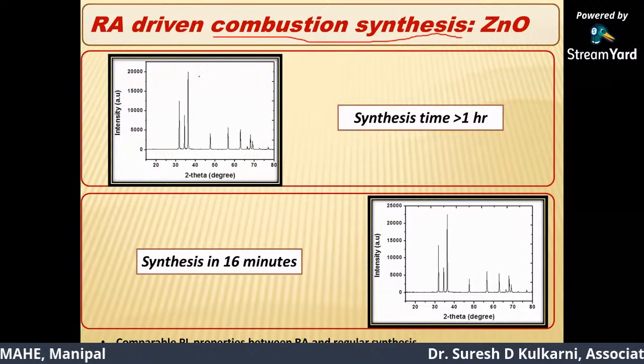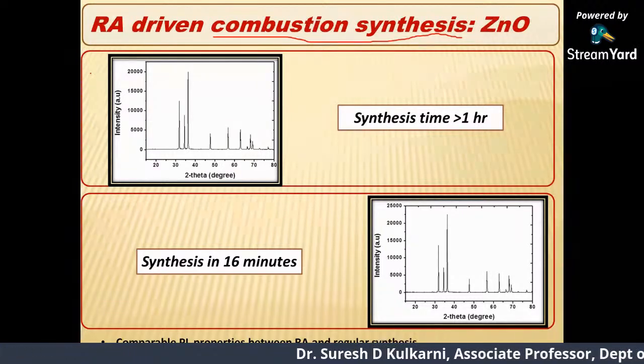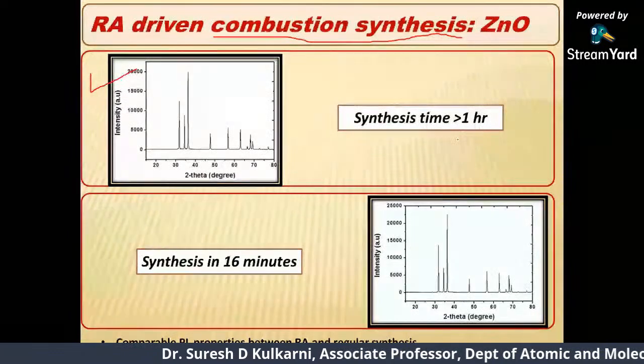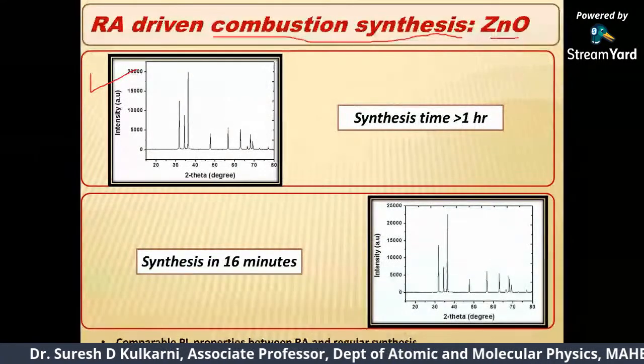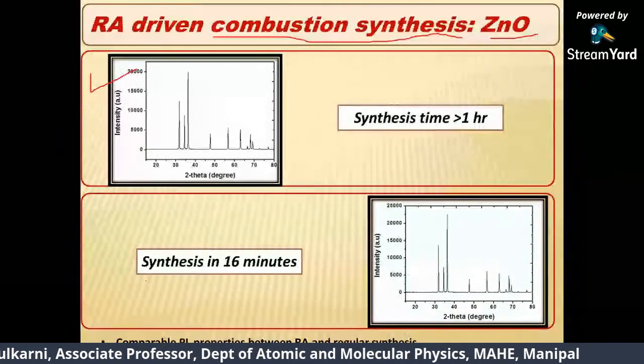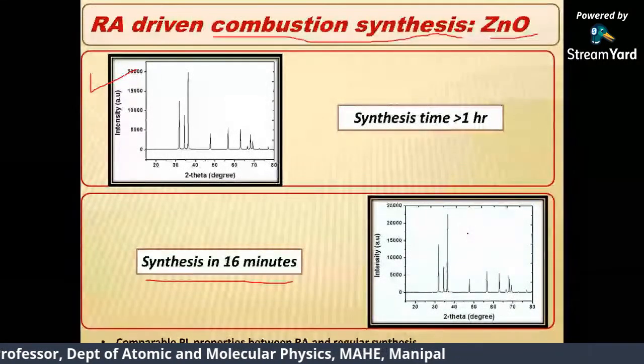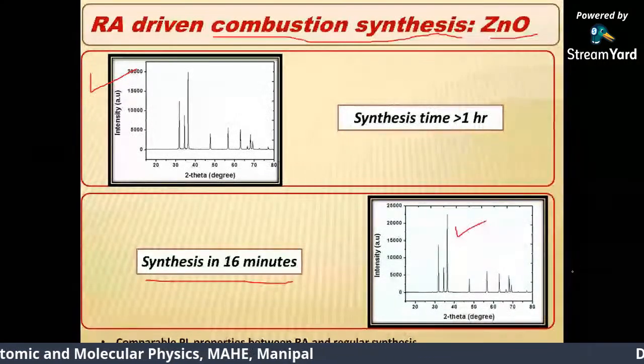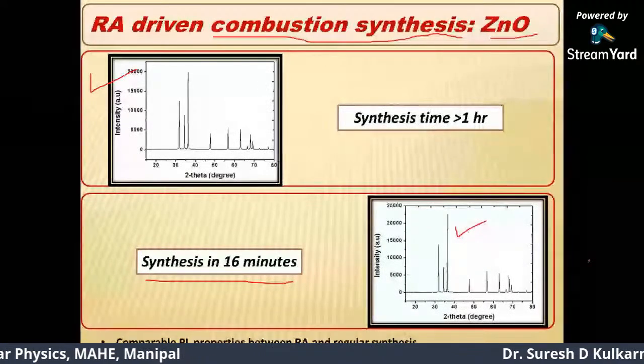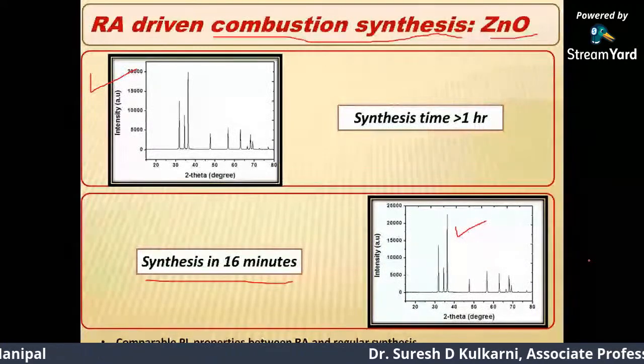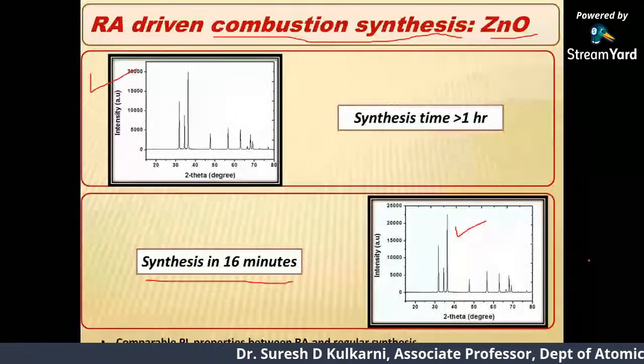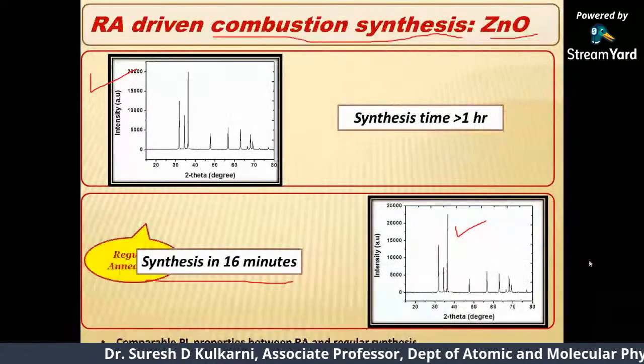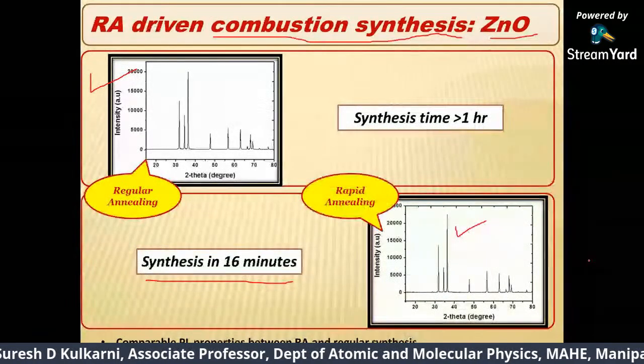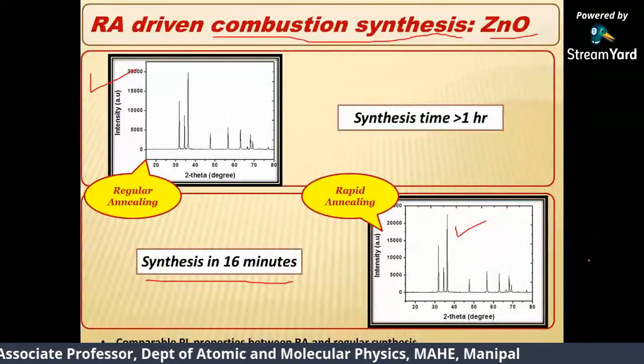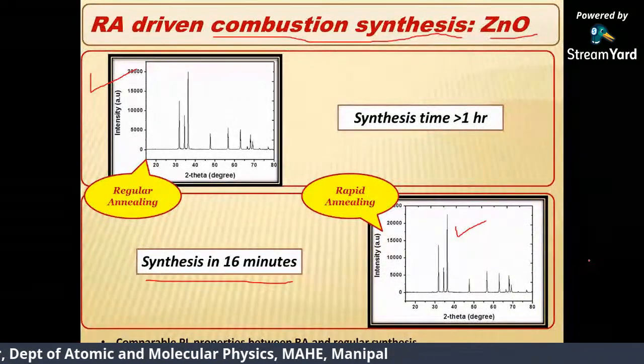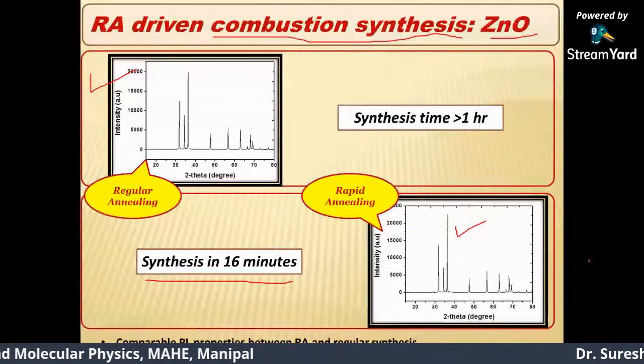And conventionally, if we do this in our laboratory, it takes about 1 to 1.5 hours to prepare zinc oxide nanoparticles, and within only 16 minutes, you can prepare nicely crystalline zinc oxide particles using a rapid annealing system. So that means rapid annealing can also drive combustion synthesis. Rapid annealing is useful, and the photoluminescent properties are also comparable with regular annealing.